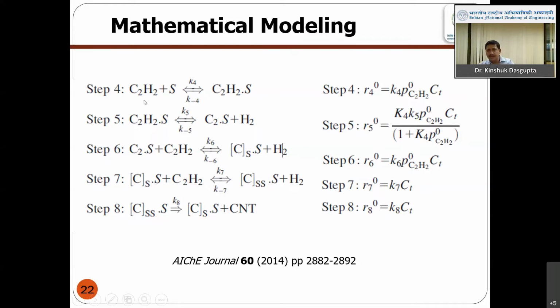As I told, acetylene is coming and reacting with S, where S means a catalyst site, and they get adsorbed. After the adsorption, there is a dissociation of the carbon molecule and hydrogen comes out. Then this adsorbed carbon reacts with excess acetylene, gets saturated, and hydrogen comes out. The saturated one again reacts with acetylene, becomes supersaturated, and hydrogen comes out. Finally, from the supersaturated state, carbon nanotubes come out and it returns to the saturated level. Except for the last step, all are reversible reactions, but the last step is definitely irreversible.